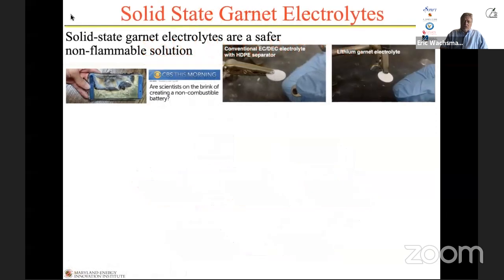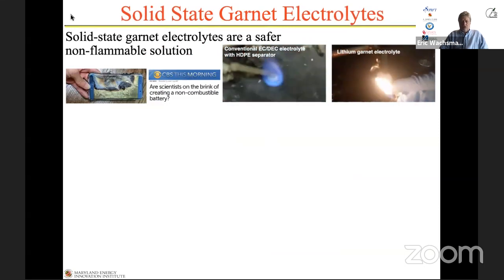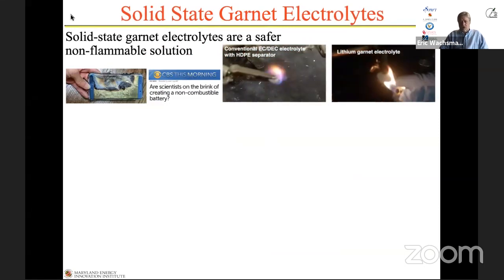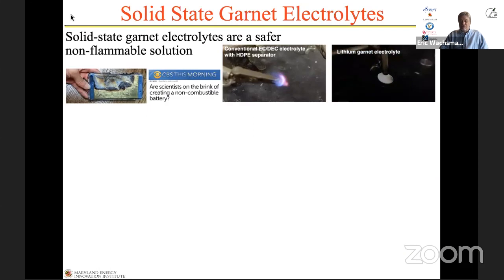To give you information about what that material is and why we do it, this is from an interview I had on CBS this morning about all the battery fires. If you remember poor Samsung, when their phones caught on fire, they had like a $7 billion capitalization loss. All batteries today are made with an organic liquid electrolyte, which is very flammable. You just saw the flame as it completely burned out on the video to the left. The video to the right was this ceramic garnet material. We held it under the same flame, and all you saw is some soot deposition from the flame itself. We fire these things at around 1100 degrees centigrade. So it's very unlikely your phone's going to catch on fire with this type of material. In fact, thermodynamically it couldn't.